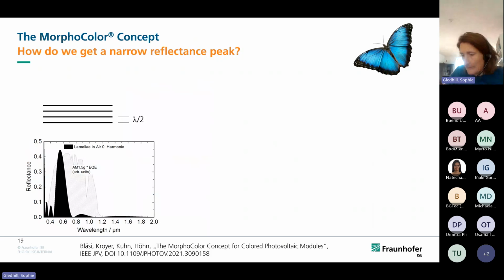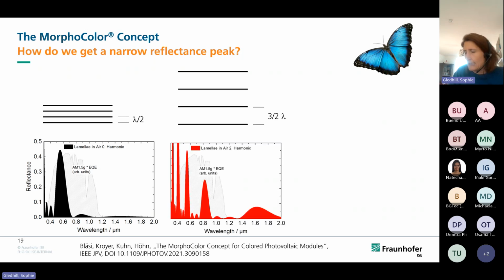So how do we get our narrow peak? The color we observe in the Morpho butterfly is caused by the lamella, which have a separation distance of d, which equates to half lambda, where lambda is the designed wavelength, or the peak wavelength that's being reflected. Half lambda is known as the zeroth harmonic. Lambda is the first harmonic. And if we take the 3/2 lambda spacing, we have the second harmonic. By choosing the second harmonic in our interference stack, we get a much narrower peak width.